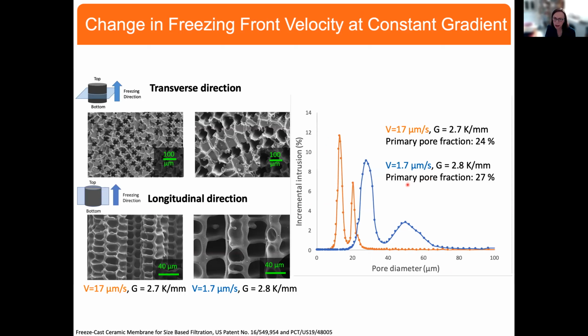And so this is an example now. If we then change the freezing front velocity, as we go to slower velocities, we're basically pushing that pore size distribution to the right to move that to much larger pores. And that's shown here in the longitudinal direction and in the transverse direction.